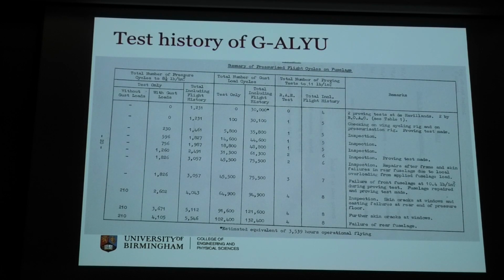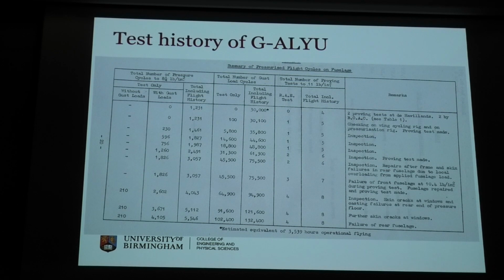Test history just goes to show that. They tested it, they kept inspecting it, they kept running it. And if they found a crack that got particularly long, they'd stop it, either drill stop at the end or put a rivet over the top of it and carry on testing. So they actually used it for a number of different inspections, a number of different cracks, and they were just chasing them through.